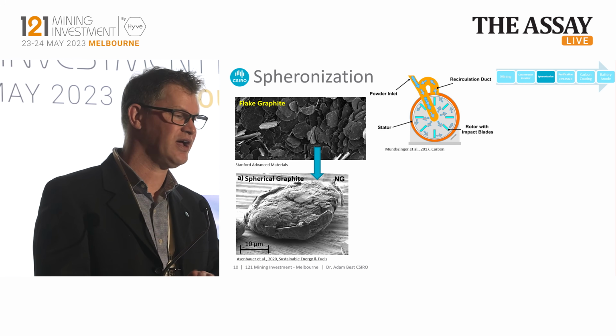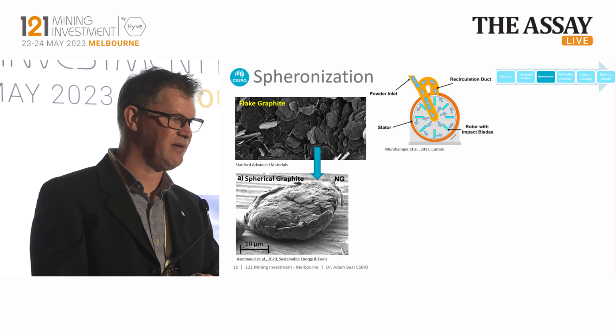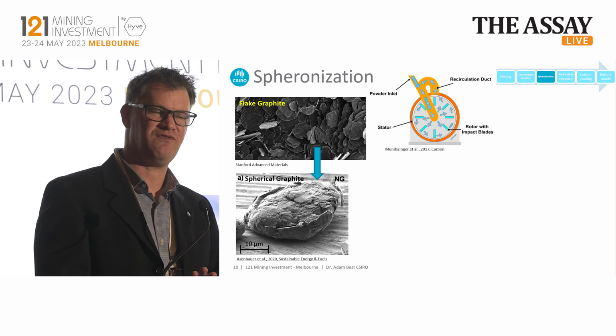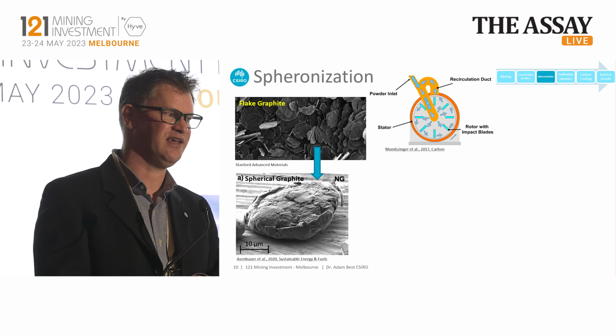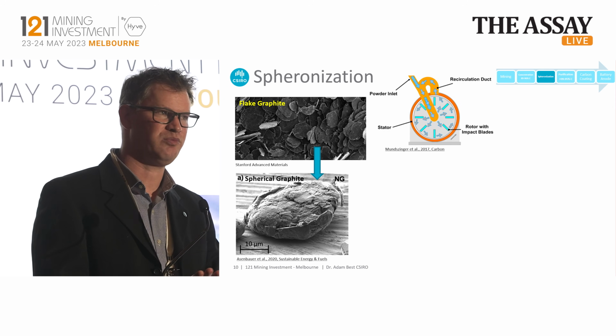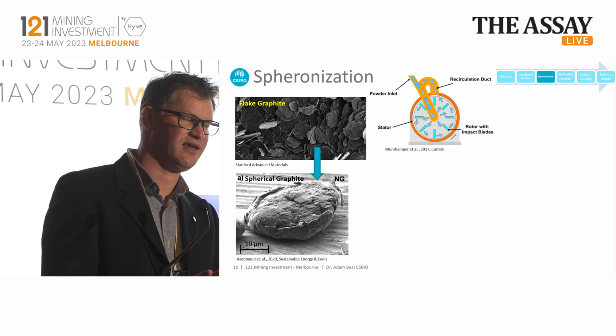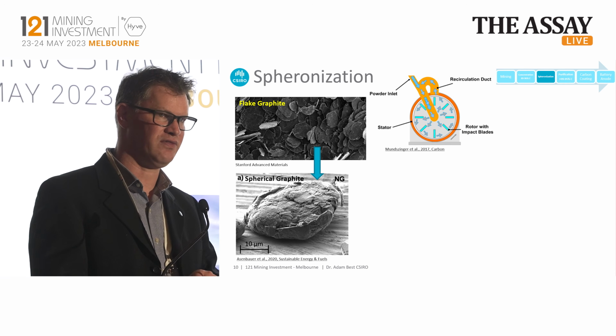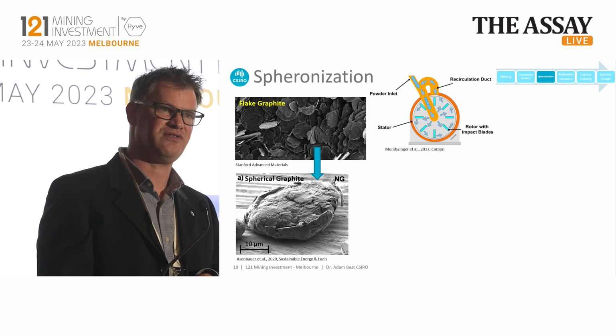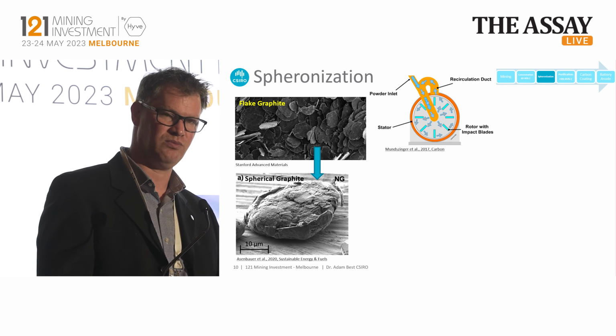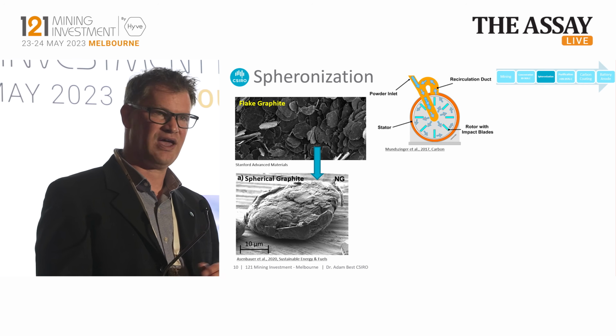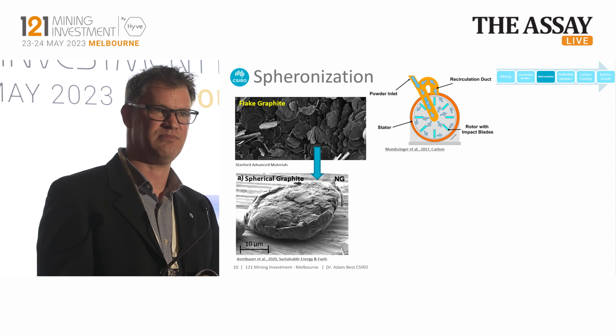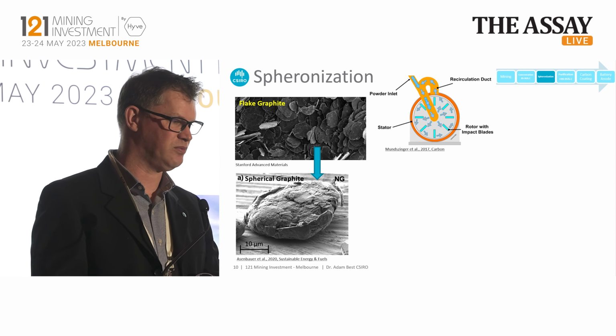Further, graphite reacts as well with the electrolyte. And so we end up with those hard edges on the graphite flakes. We get what we call a solid electrolyte interface. And this material is the decomposition product of the electrolyte on that flake. And you want to minimize the amount of those decomposition products, because those decomposition products actually mean the battery is less efficient, will have shorter cycle life, and won't work as effectively. So for that reason, we spheronize to get rid of as much of those hard edges and the like to actually make that process as efficient as possible.